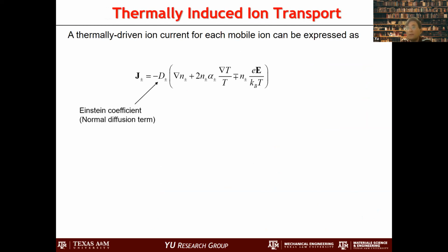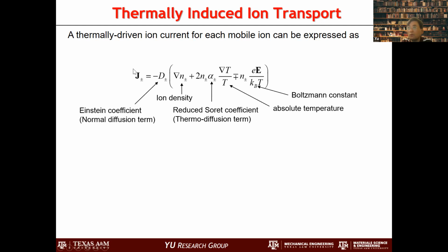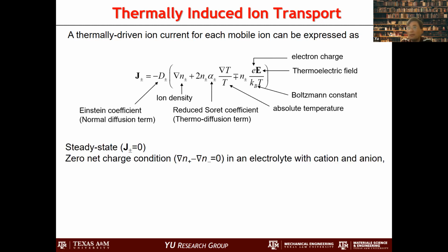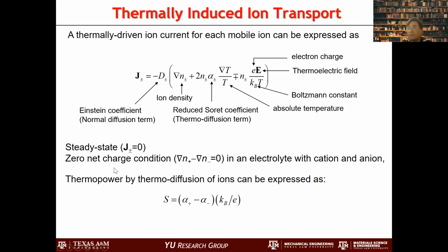So if you look at the governing equation, it is basically ion transport whenever you have a temperature difference. This is basically the current associated with ions. And what was interesting here is this kind of complex equation. But at the end of the day, what we are interested in is the steady state operation, which makes this current zero. And then with the zero net charge condition, which is oftentimes the case, you end up with this. This S is what you have seen before, which is the thermopower.